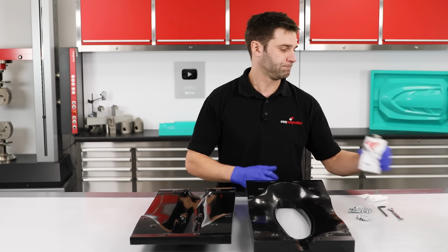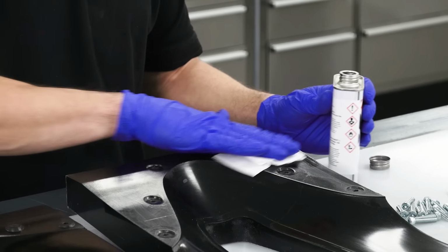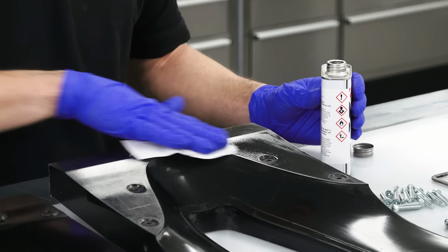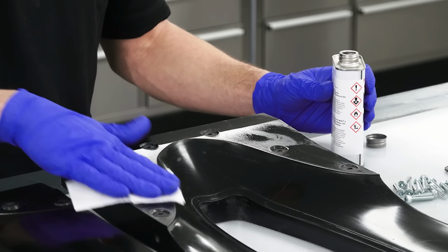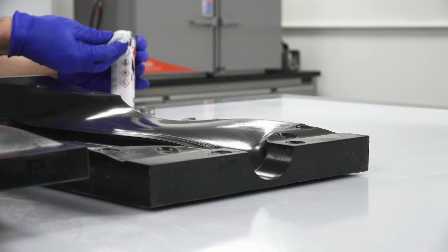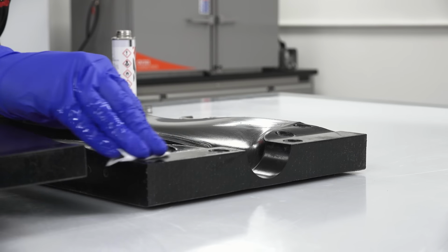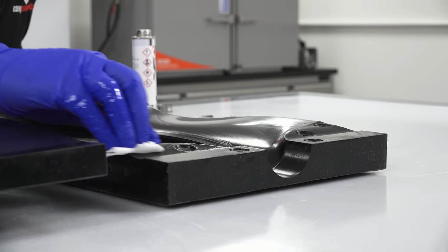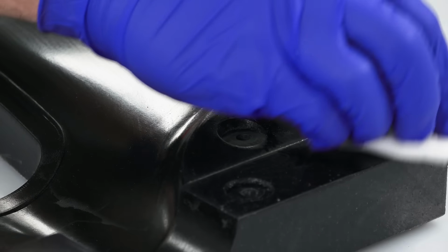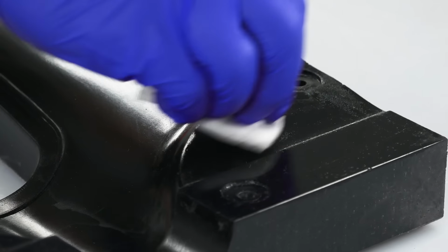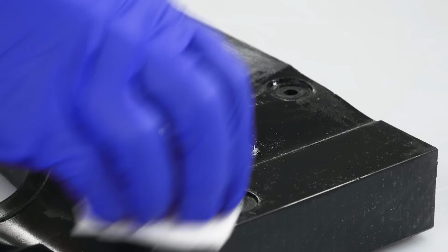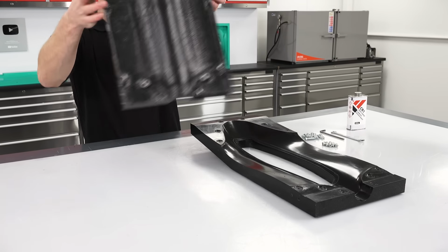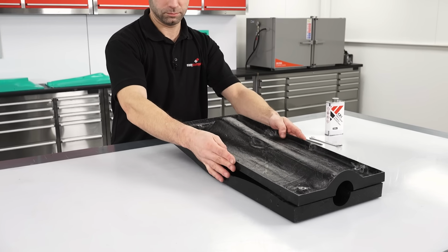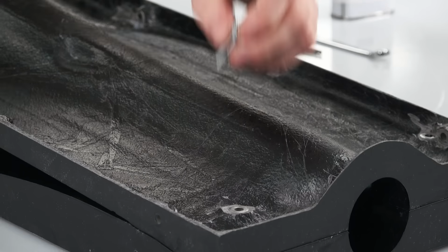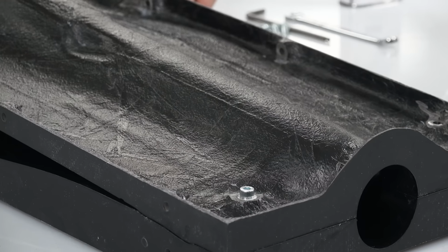perfectly. Whenever you're bolting a split mould together for post-cure, whether it's a pre-preg mould like this or really any other system, it's important to apply a thorough application of CR1 release agent to the mating flanges. Otherwise you can find that the temperature increase of the post-cure can soften the resin or gel coat sufficiently to cause untreated flanges to stick slightly to one another. With the release agent applied, the mould sections can be bolted together using the M6 bolts and dome nuts, which are size 4 and supplied with the MB6 bushes.